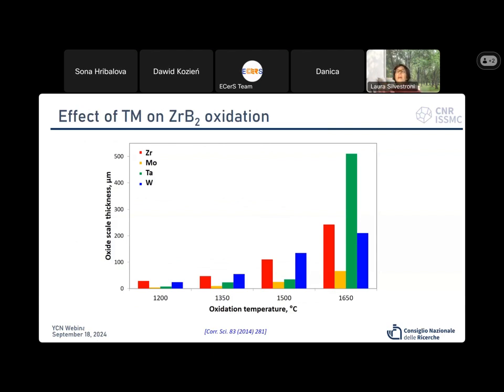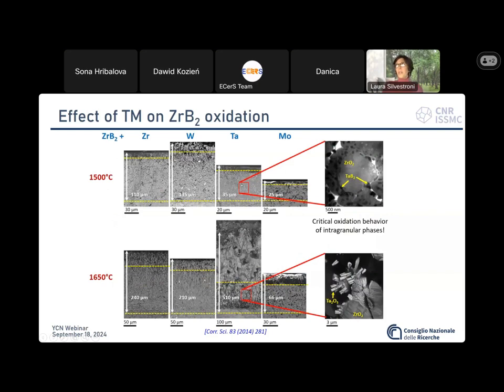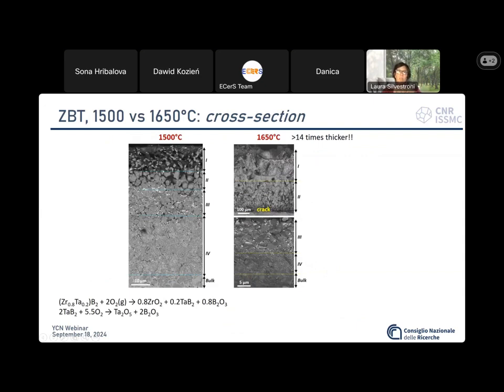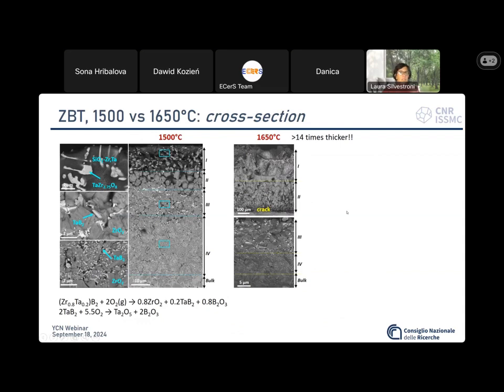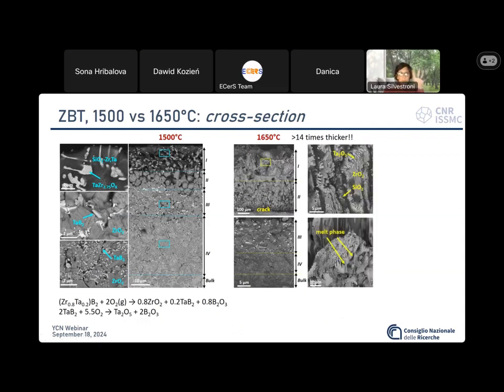Here we have zirconium diboride additivated with zirconium, molybdenum, tantalum, or tungsten silicide, oxidized at 1200, 1350, 1500, and 1650. You can see here that what works really well up to 1500 degrees C is not really optimal if you increase the oxidation temperature a little bit. And this is related to the intragranular phases. So I would just concentrate on this most striking example with tantalum. And here in the cross section, we can appreciate a very complex microstructural architecture at 1500 and 1650 degrees C. Without entering into details, we have a mixture of molten glass, solid phases, polytypic transformation, dissolution and reprecipitation. Many things are happening here.